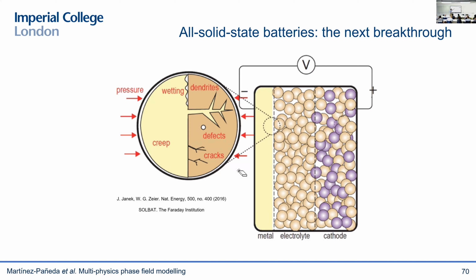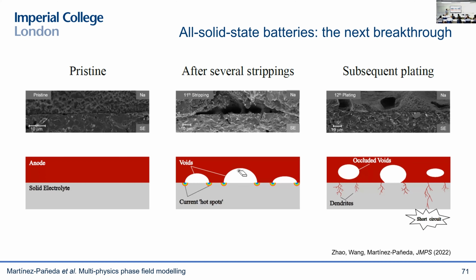In particular, the problem is the dendrite, these needle-like structures that generate at the lithium metal and then propagate all the way into the cathode, and then they cause the short circuit. And the way this works is as follows. These are some very nice SEM experiments from the group in Oxford. Every time you discharge the battery, you have stripping. So you're removing lithium from the anode.